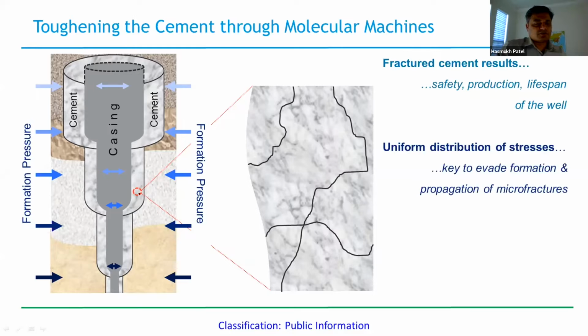To tackle those kinds of problems, the best idea is to make sure that whatever stress is generated because of this pressure difference is uniformly distributed throughout the matrix of the cement. That is the key to making sure there is minimum formation or propagation of micro cracks. Currently, we generally use latex, like rubber-based particles, or some polymeric materials which show elastic properties. We put those into the cement to make sure it has some flexibility and can distribute the stresses uniformly. However, the main disadvantage associated with the current system, the latex or the polymeric materials, is the long-term stability.